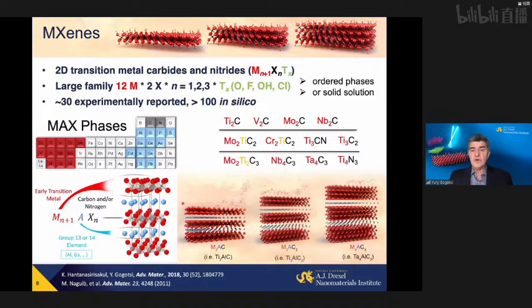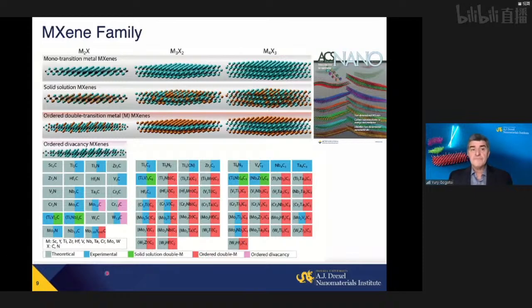And since they have now a transition metal on the surface, and aluminum, say, or silicon or other element is etched away, the transition metal won't remain unterminated. If you use etching in aqueous media, we will get oxygen, OH, or fluorine, HF, chlorine from the HCl acid. If you use molten salt, you can get other surface terminations like halogens here. But the idea is we get structures with those surface terminations. Moreover, we can make not only pure structures, we can make atomic sandwiches where one element like molybdenum is on the surface, another element like, for example, titanium is squeezed in this sandwich in the middle.